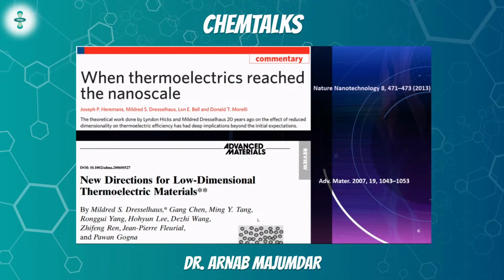When we scale down from higher dimensions to lower dimensions, the boundary scattering effect increases, which eventually decreases the lattice thermal conductivity. And keep this in mind from the previous slide, that the lattice thermal conductivity, kappa L, was in the denominator of that one equation that I showed. That means in order to increase ZT, I need to make my kappa L, or the lattice thermal conductivity, as low as possible. Okay?